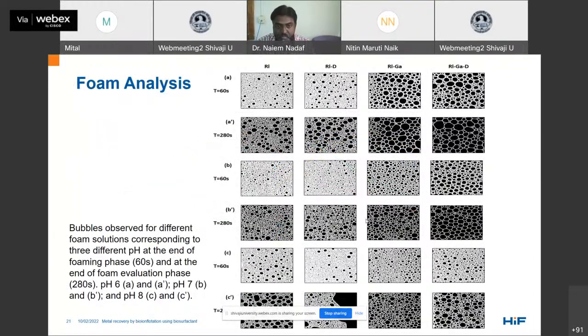And as I said, the foams are constantly changing systems. Here, the upper rows like A, B, C are for different pH, pH 6, 7, and 8. The upper rows are for the pictures taken at the end of the foaming stage, whereas the lower ones like A dash, B dash, and C dash are for the pictures that were taken towards the end of the evaluation phase. So here we can see that the foams with rhamnolipid and decanediol are very fine. They have very fine bubbles and are very spherical, and they remain spherical even at the end of the evaluation phase.